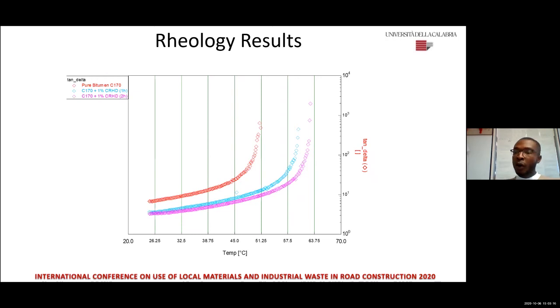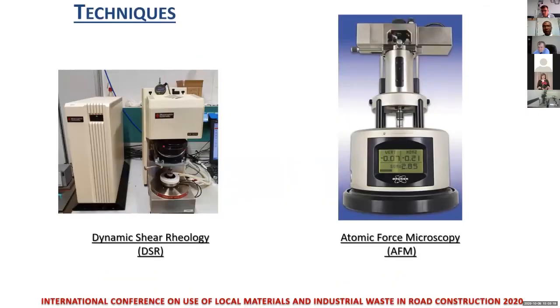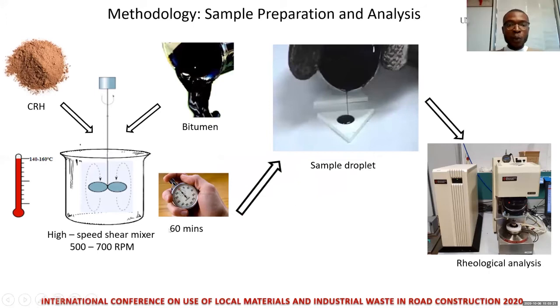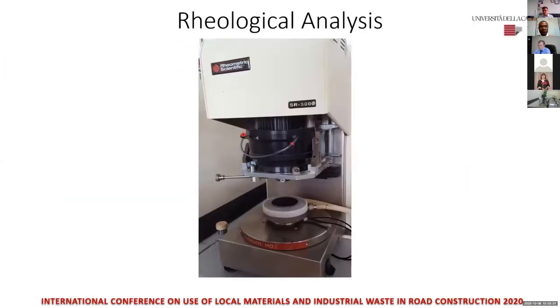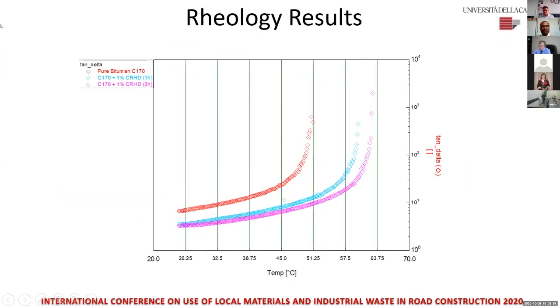Now, when we were preparing the bitumen, if you remember, I said that we leave it under agitation for 60 minutes, that is an hour, in the sample preparation. We also tried to see if we leave the preparation time for more than 1 hour. We tried an agitation time of 2 hours, which gave us these results, to see if it can give any significant effect in the final sample.